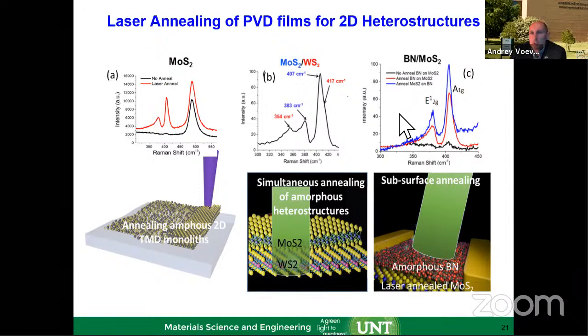But what we are actually doing right now, to protect molybdenum disulfide and tungsten disulfide from the surface, we're growing a molybdenum disulfide structure, and then we grow amorphous boron nitride right on top of it. In PVD, just one step after another, just two different targets. And then after extracting from the chamber, we anneal it through the boron nitride. The interesting part is that boron nitride is a wide band gap material, meaning it is very transparent to the laser beam, which is absorbed by molybdenum disulfide and by the PDMS. This allows us to protect the surface from oxidation.